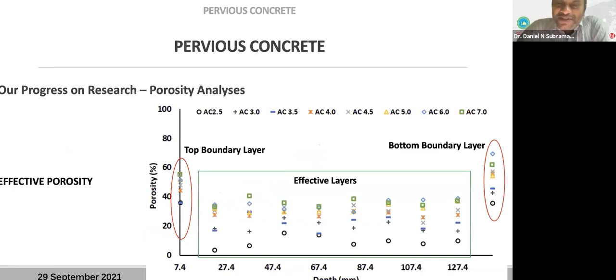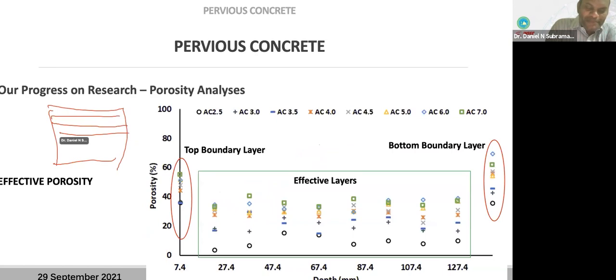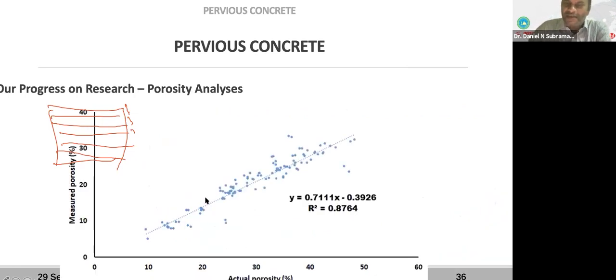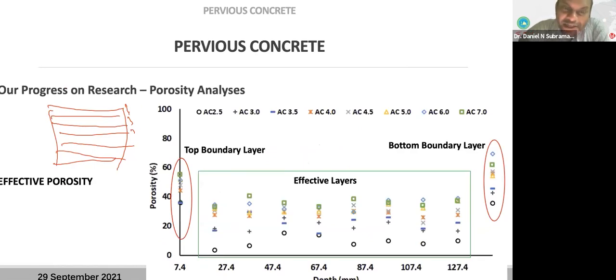Right. So now in this one, what we did is we took the cube, the picture that you saw, and we split it into 10 strips like this, horizontally. And we found the porosity of each strip, so that is porosity with depth. The picture that you see here is the porosity of the 10 strips with depth. On the x-axis you have depth, and on the y-axis you have porosity. So you can see there's significantly higher porosity in the top and the bottom layer. You can find it here and also at the end.